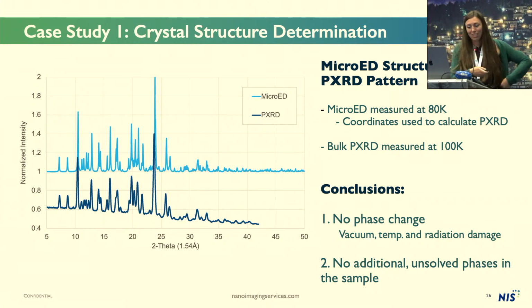But from this comparison, we can conclude that there was no phase change from the bulk material to the micro-ED structure. So exposing this to vacuum in our microscope, the temperature, and any radiation damage did not seem to have changed the structure, which is great. And then we also see that there aren't too many extra little peaks in there. So we think that there's only one phase in this bulk powder, and then we solved it. So that's what we conclude.